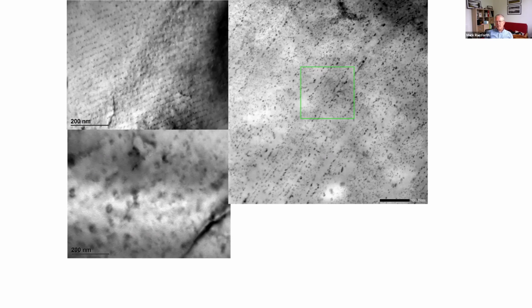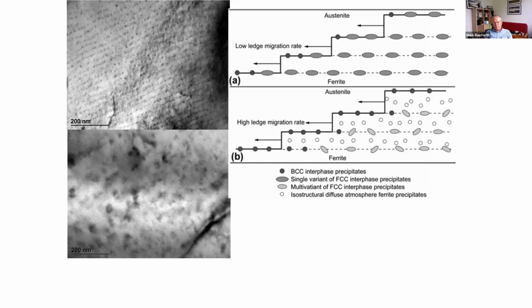Now, this is nothing new. Interphase precipitation was studied extensively in the 80s. It was a very popular subject then, but it never really made its way through to a commercial product. So what we did with this is to play around with the compositions, add a bit of magic dust, and to end up with an alloy that was really quite lean. The cost therefore was low, and we could produce, as I say, a very high number density of very fine precipitates within the structure.